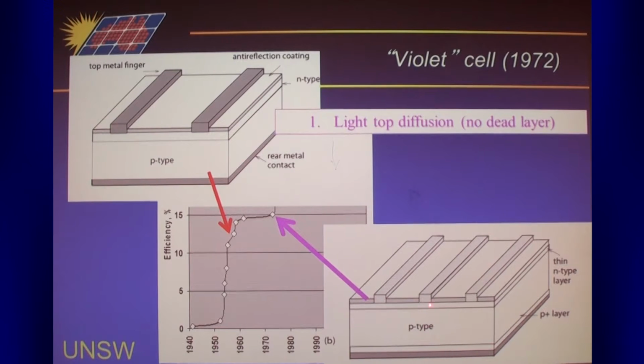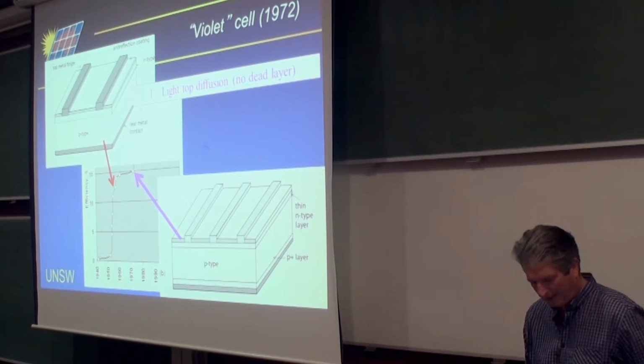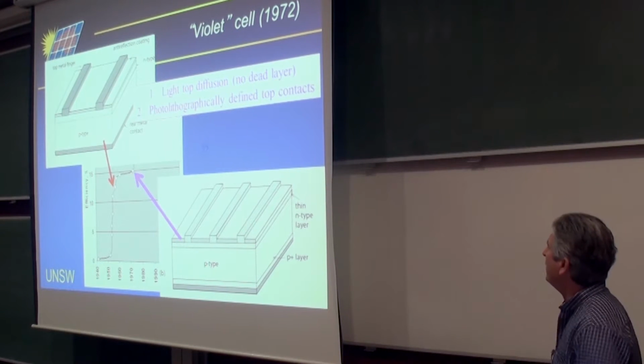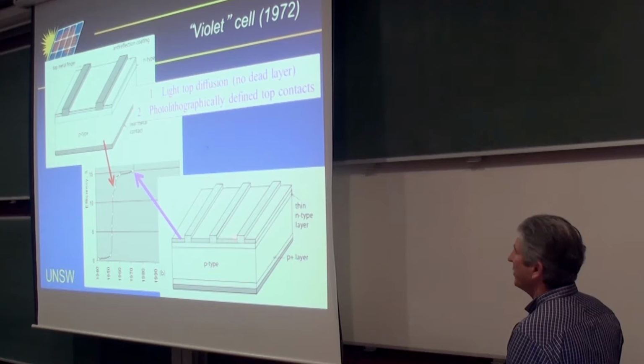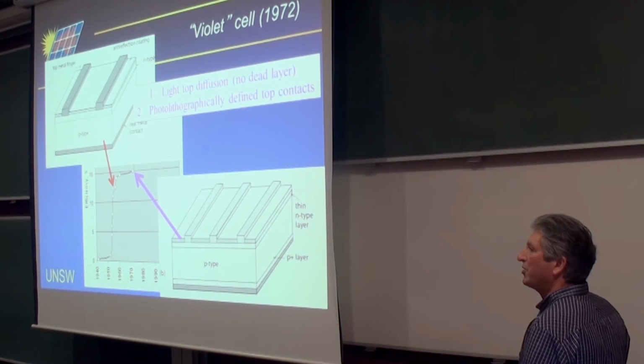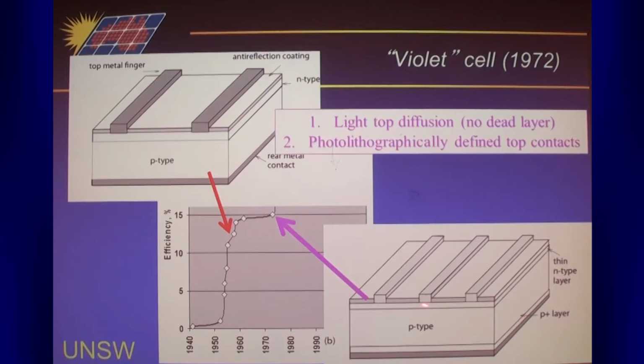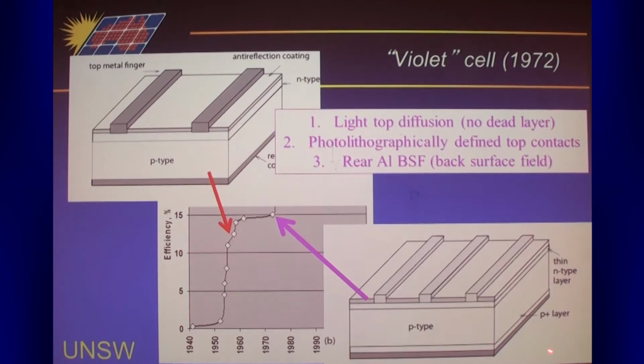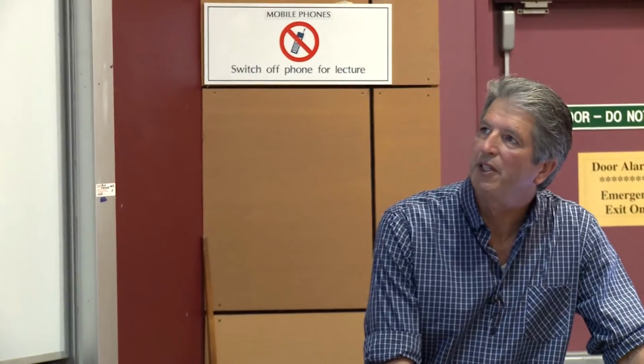So the things that were done, and we'll talk more about this in the next phase of the lecture, a lighter diffusion here to get rid of that dead layer I mentioned that formed at the surface. And then photographic techniques were used to define these fingers so they could be made much narrower, put closer together, and this reduced the resistance penalty from going to a lighter diffusion in this region here. This doped region near the rear, by heating an aluminium layer on the silicon rear, you could actually get it to cause the silicon to melt at quite low temperature, and then when it re-solidified, it was doped with aluminium, which is a P-type dopant in silicon.